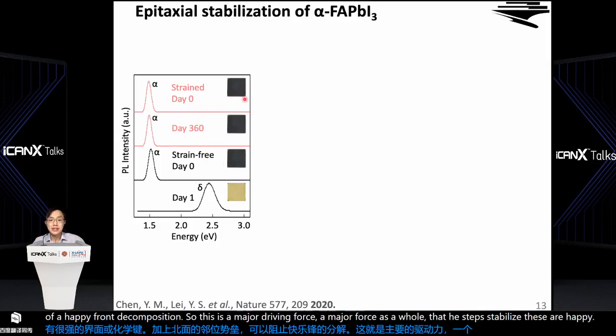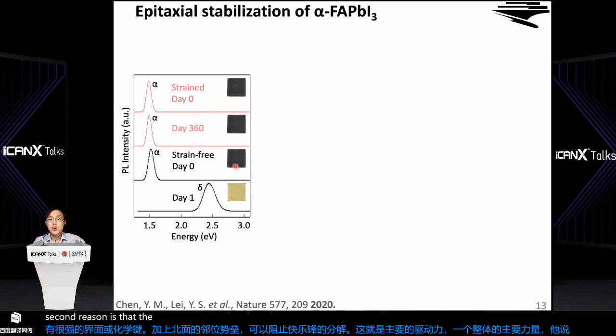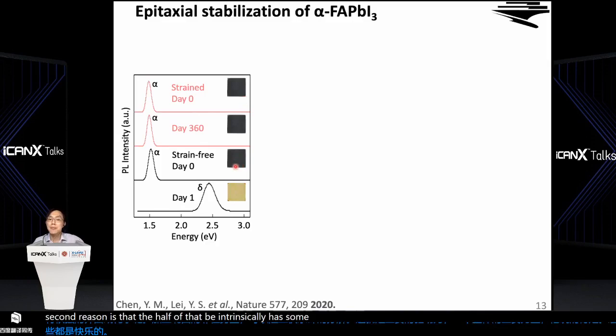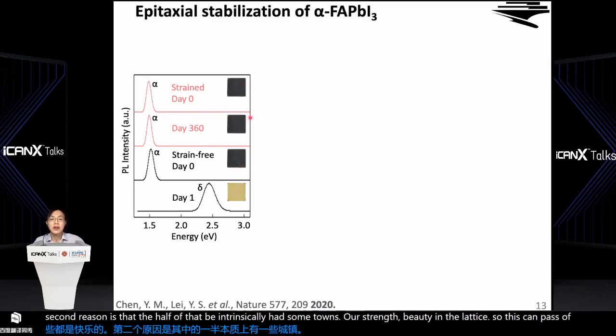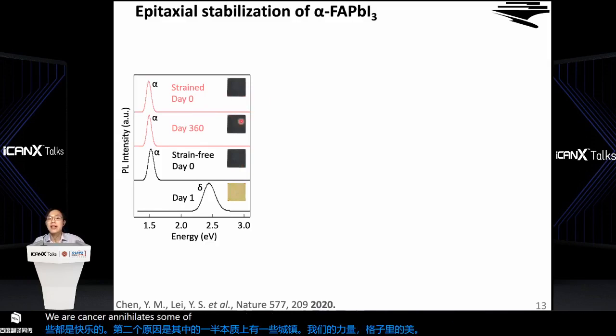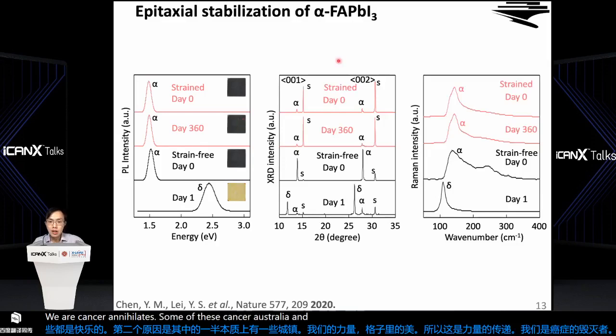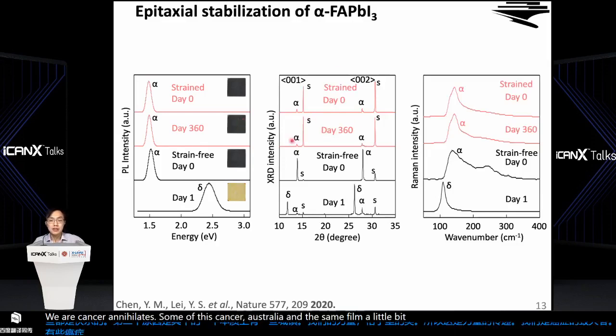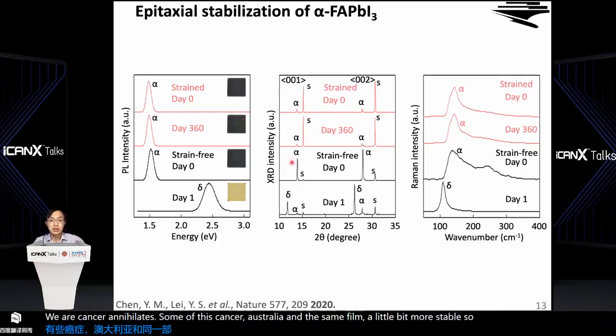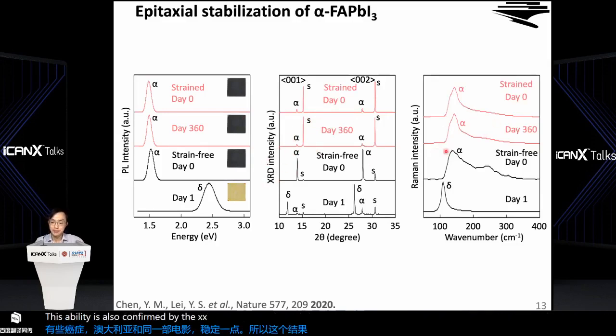The second reason is that this alpha FAPI intrinsically has some tensile strain built into the lattice. So this compressive strain will annihilate some of this tensile strain and make this thin film a little bit more stable. So this enhanced stability is also confirmed by XRD and also Raman spectroscopy.